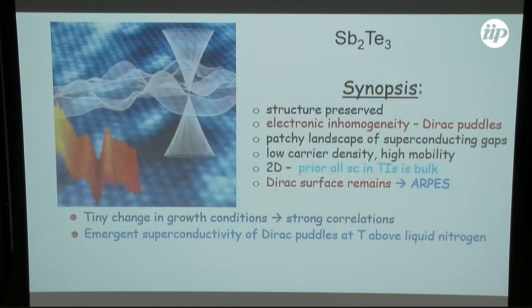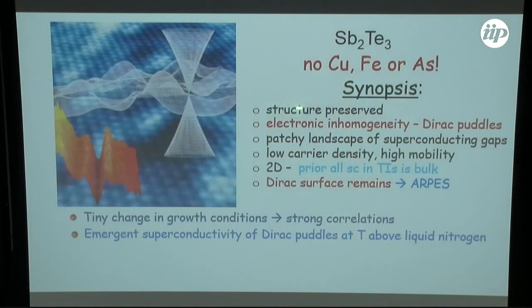So let me just, before I go on, give you a little synopsis. The system we're looking at is antimony 2 tellurium 3. And I would like to make sure there is no copper doping, there is no iron there, and there is no arsenic there. So nothing that can give you some sort of superconductivity by doping. And the key thing that I've talked about before is that we grow our own materials. So we do modify Bridgman growth. And it turns out, again, we discovered that a very tiny change in growth conditions gave us very strong correlations, while structure, both crystal structure and Dirac structure, was preserved.